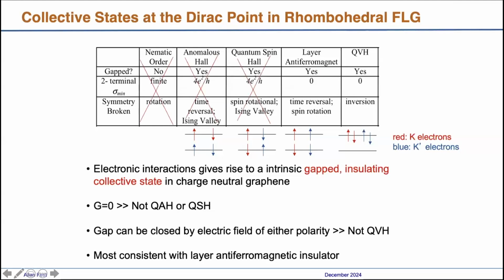So this basically eliminates the nematic order, the anomalous Hall state, and the quantum spin Hall state, leaving us with... and the fact that an electric field of either polarity can destroy this state removes the quantum valley Hall state. So this leaves us with the layer antiferromagnet, meaning the top and bottom layers are spin polarized. If you have more than 2 layers, the middle layers are just sort of inert and don't do too much.